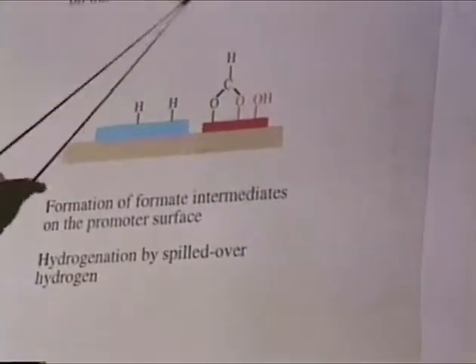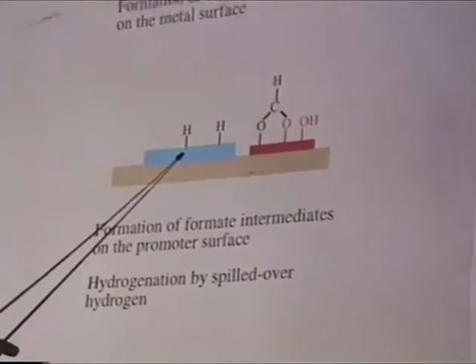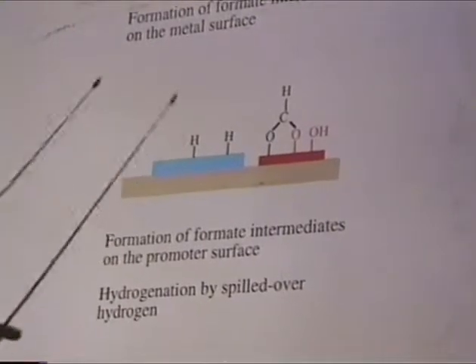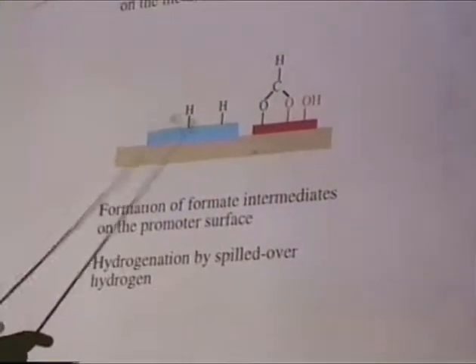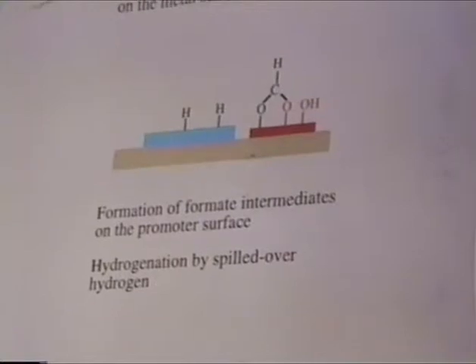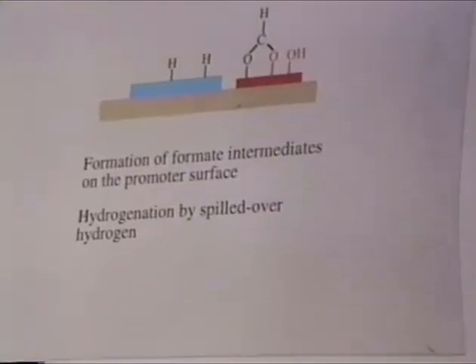In the industry, they just added the methanol, and then of course in this step you get the methyl formate, and there you go. In our case, all it needs is a very slow site which starts the cycle, and then you have catalysis, and the mechanism would be that you make your formate here on the promoter metal oxide, on the calcium oxide for instance, and then you make a methyl formate. This goes through the gas phase to the metal somewhere. Doesn't matter if it's close or far away. Then you have the hydrogenolysis there. So the only function in this case of the metal is to deliver hydrogen atoms, do the hydrogenolysis.